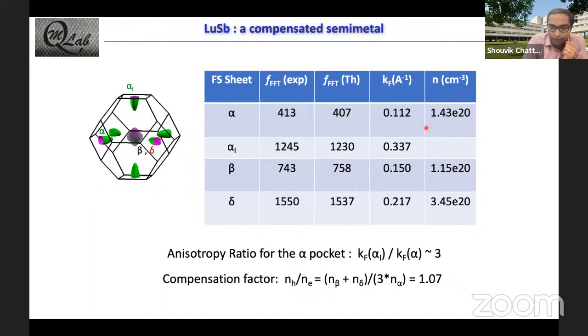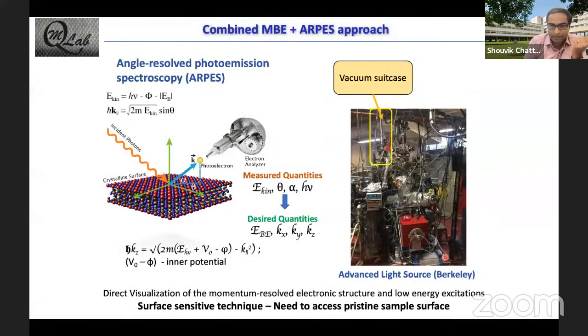And when we calculate the carrier densities, we find that at least in the bulk limit, there is a very good compensation in the sense that you have almost equal numbers of electron and hole-like carriers. And we can also get an idea about the anisotropy ratio, which is basically a ratio between the semi-major and the semi-minor axis of the ellipse, which is about 3, which again matches very well with our DFT. So no surprises here still, at least till this point.